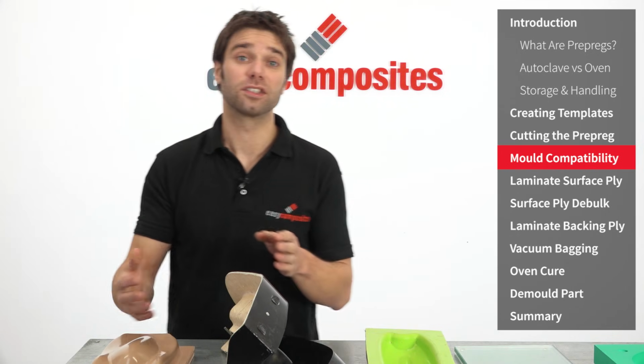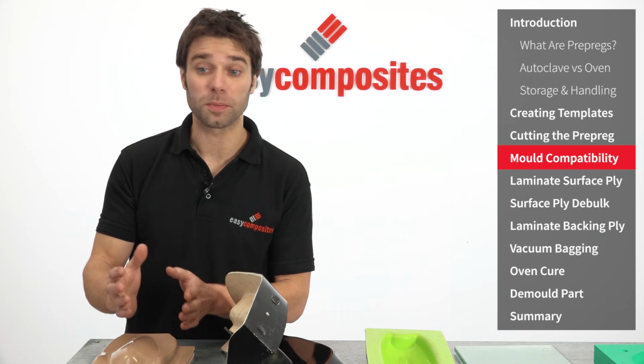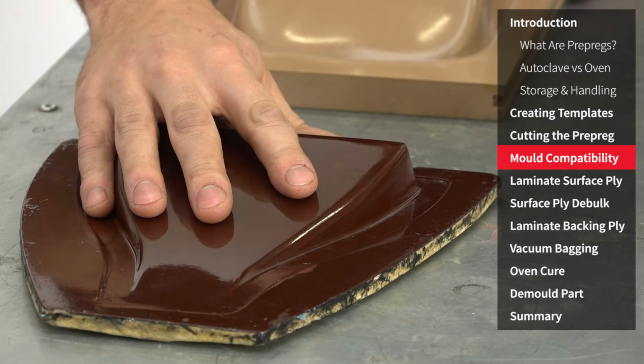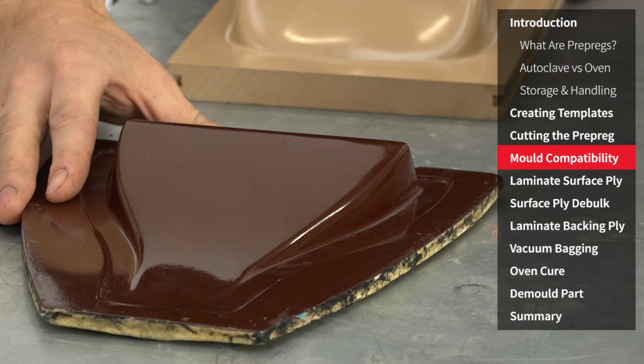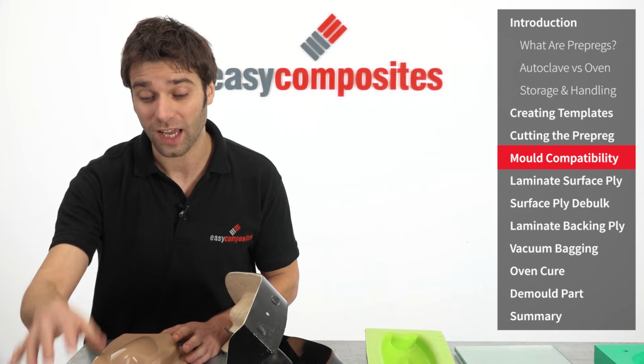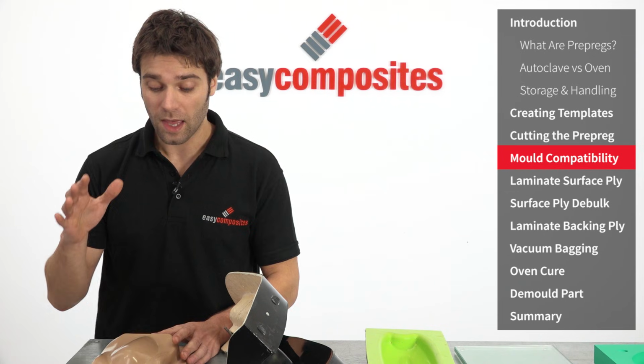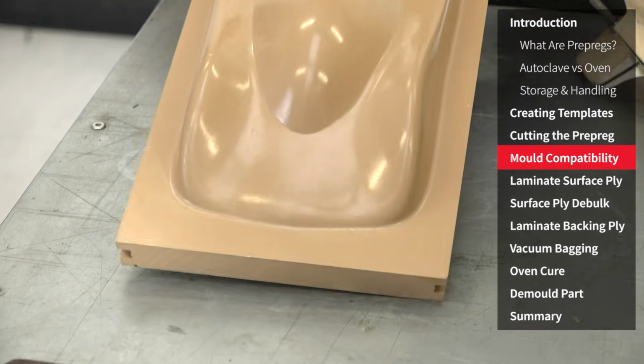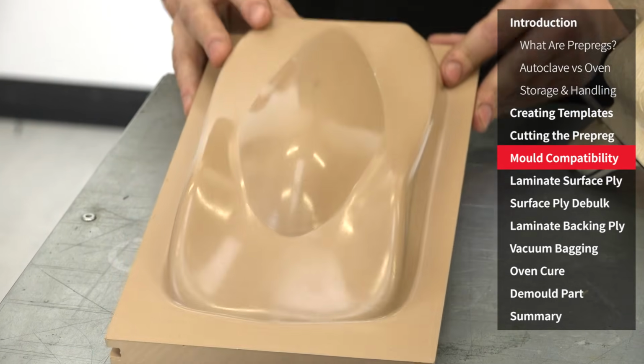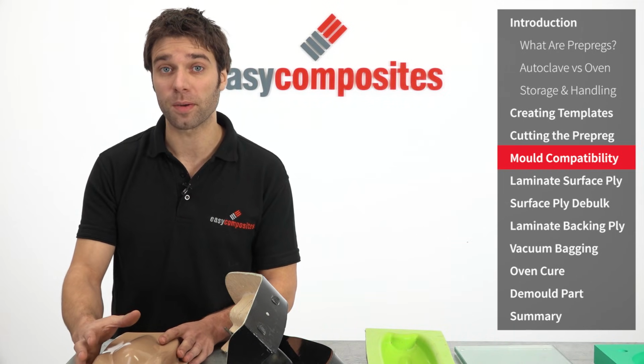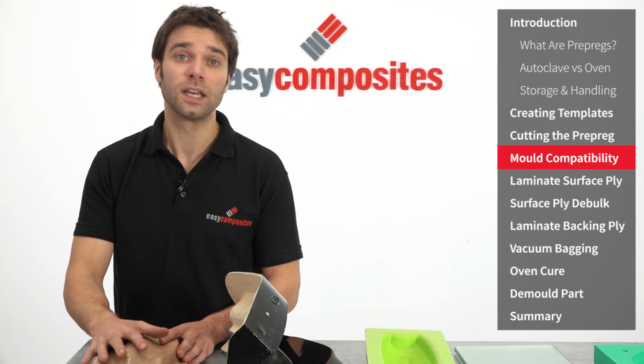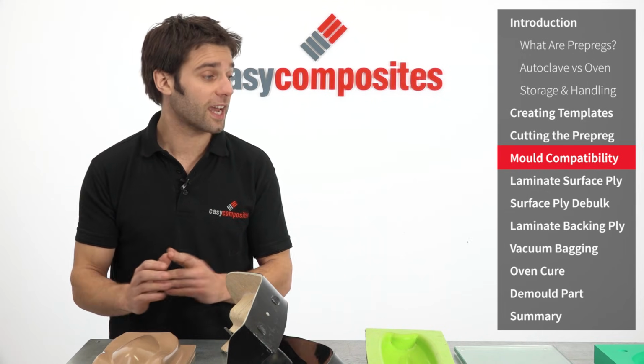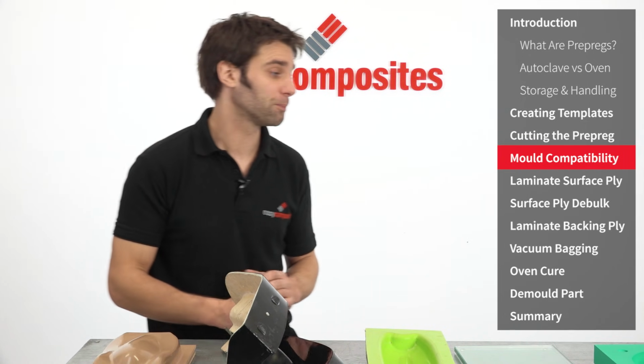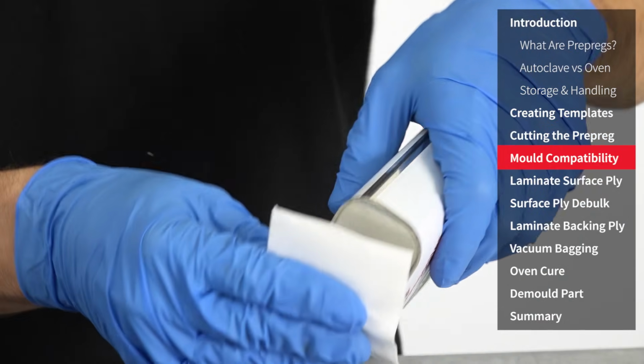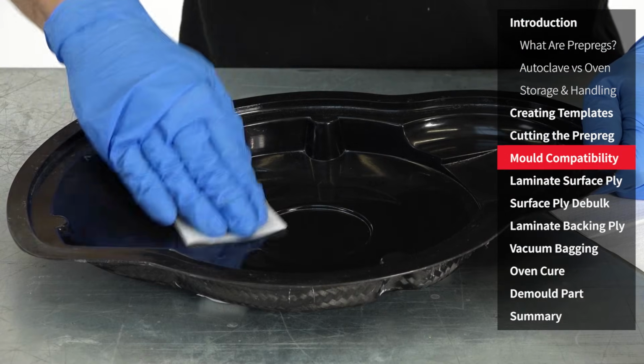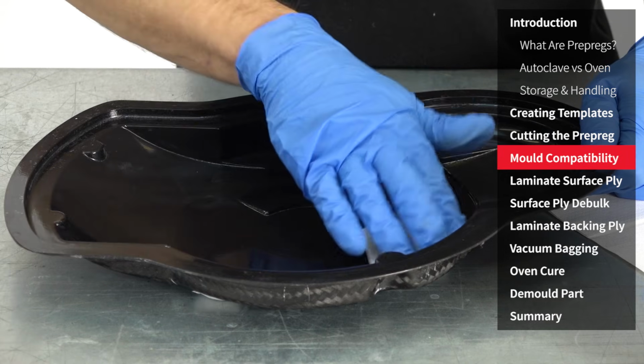There are some types of materials that absolutely can't be used with epoxy pre-pregs. So we have here a polyester mould tool, so that's a conventional fiberglass mould. This can't take the temperature and you're likely to get severe release issues. The other material we have here is polyurethane model board. This is widely known to cause cure inhibition with epoxy pre-pregs, so this also can't be used. So we're not going to have any of those problems today as we're using the epoxy pre-preg mould. Before laminating, easy release agent should be applied to the mould. Please refer to the product datasheet for application guidelines.